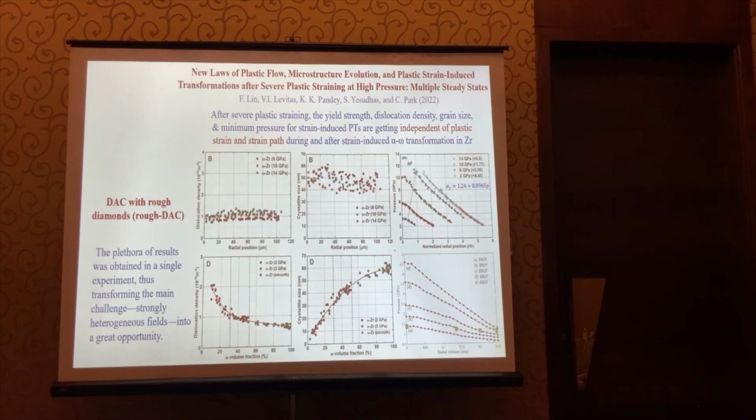And you see it's independent of plastic strain path, and it's isotropic. And still with this relationship, we are able to describe all our pressure distributions. At each point, we have a different plastic strain tensor and plastic strain path, which proves independence. And even more, during phase transition, we found that dislocation density and crystallite size depend solely on the volume fraction of high pressure phase and are independent of plastic strain path, and even pressure.